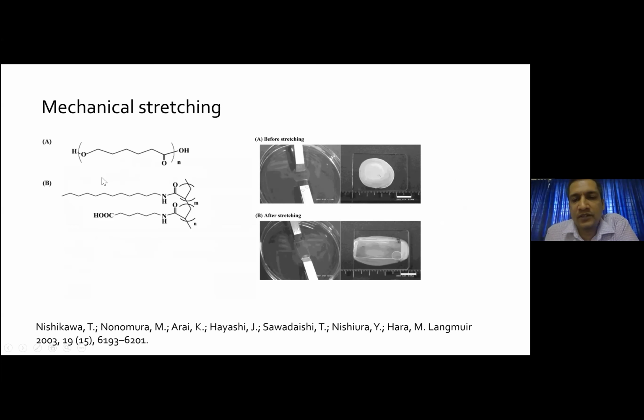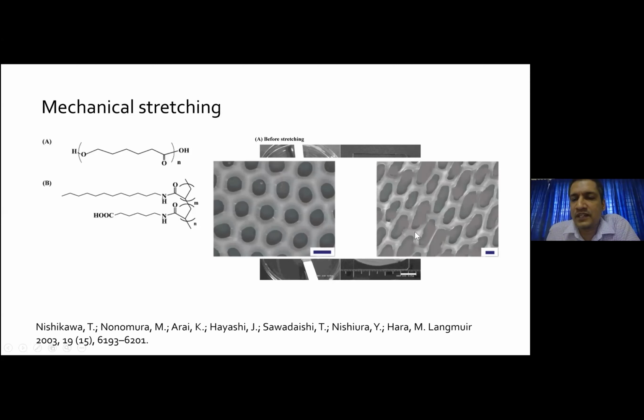The polymer caprolactone is known to show some kind of elastic behavior, and they used this polymer in the presence of an amphiphilic polymer of N-octyl and N-carboxylic acrylamides. They used this amphiphilic polymer to blend in various ratios and bring in the elasticity, and they prepared the breath figure without disturbing the surface of the thin film. After that, they could stretch the polymer slowly. Once stretched, they could go from circular to elongated or ellipsoidal pores, and by changing the direction in which the stretching is applied, they could generate several varieties of pore dimensions,